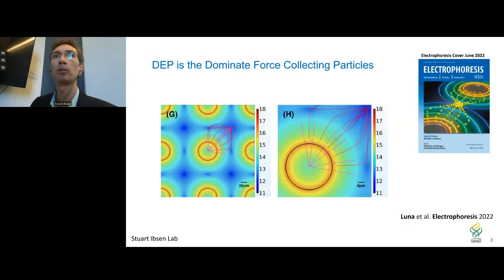Now, we've done a lot of work tracking particles as they're being collected. And here you can see a computer model of the electric field, or the electric gradient, around the electrodes themselves. The red area shows where the dielectrophoresis forces are going to be high, in what we call positive dielectrophoresis. And the dark blue areas are regions where there's going to be a low field gradient. So we were able to theoretically calculate where the particles should travel as they're being collected. And that's these thick red lines here where the particles ought to move. And then these dotted lines around it show the actual trajectories of where the particles went.